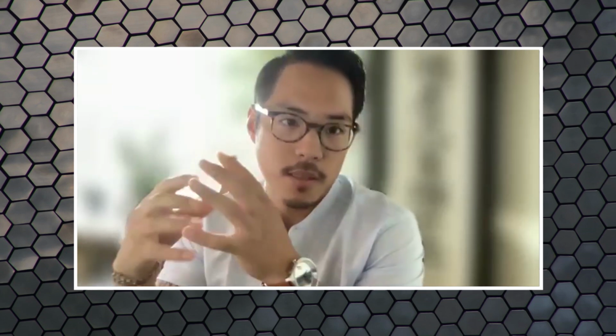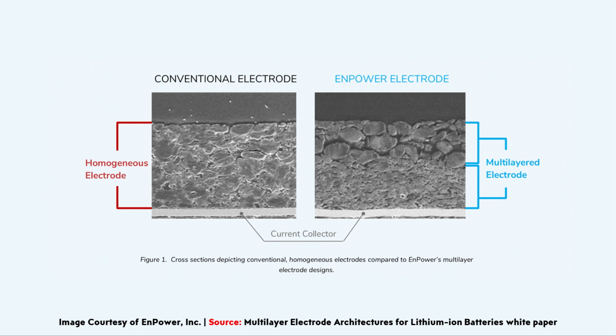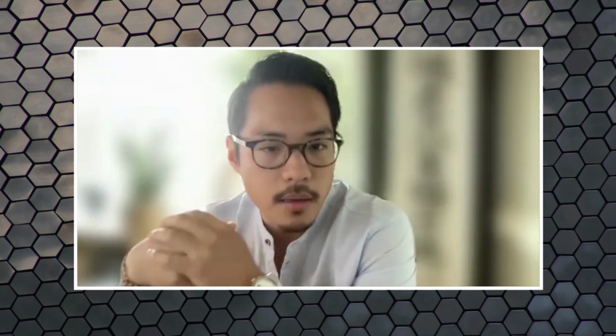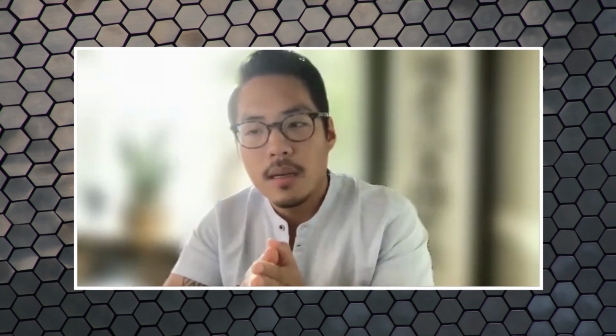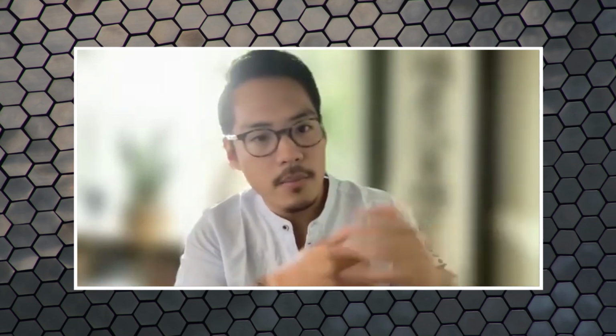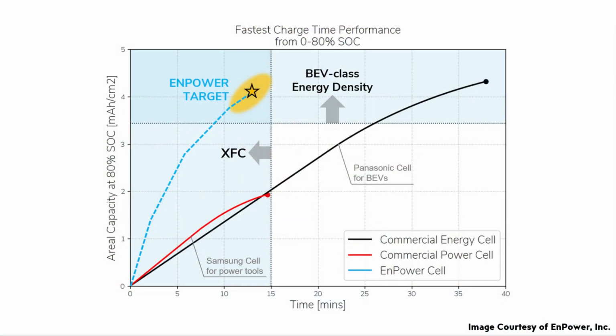So if we can enable the surface of the electrode to be more, for example, porous, using that same example, and to enable a more rapid transport of lithium ions to access not just the surface of the materials, but all of the materials in the electrode, then we can balance the state of charge throughout the thickness more evenly and prevent lithium plating from happening. So that's fundamentally how multi-layer technology works. Of course, if you blasted it with some current that it wasn't designed for, you're still going to end up with the same result. But the key difference here is that since these electrodes are now intelligently designed from a first principles point of view, you can increase your operating boundaries in the power regime while still maintaining a certain energy density. So that's our vision of getting to a 300-mile range vehicle, but still have the 15-minute fast charge capability.